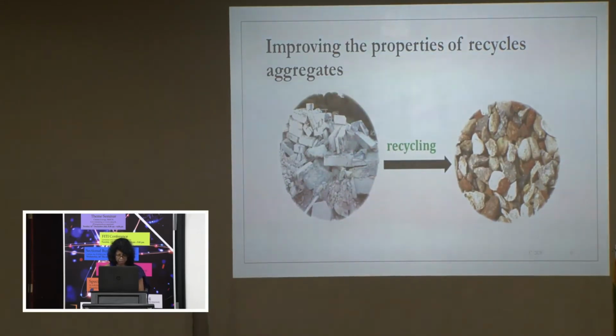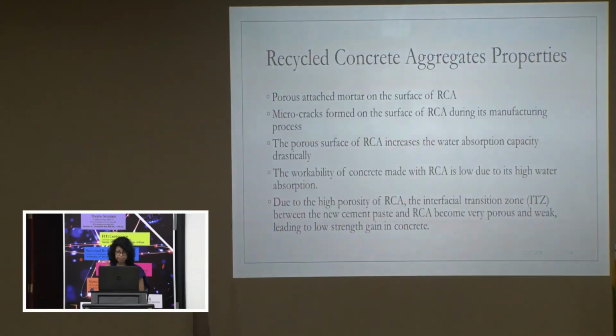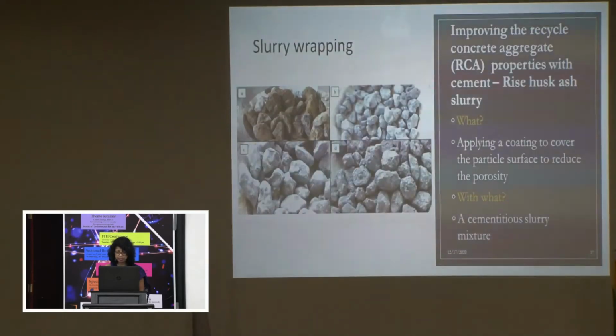It has been found that if the bond between recycled aggregates and the new cement paste could be strengthened, the negative effect it has on the properties of concrete can be negated. It would be possible to enhance the strength of the aggregate and reduce the water absorption at the same time if the pores present on the surface of recycled aggregates could be filled with finely divided mineral admixtures. This will strengthen the ITZ, thereby strengthening the concrete made with it.